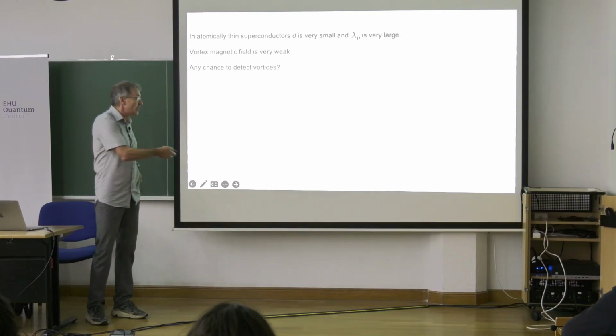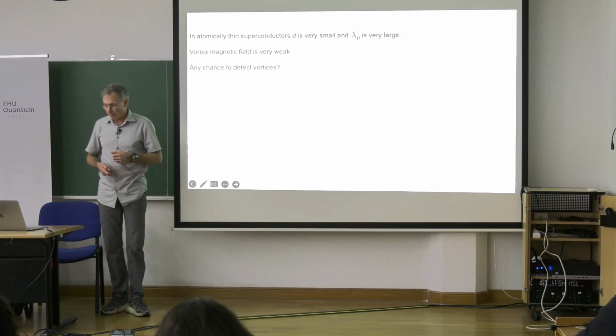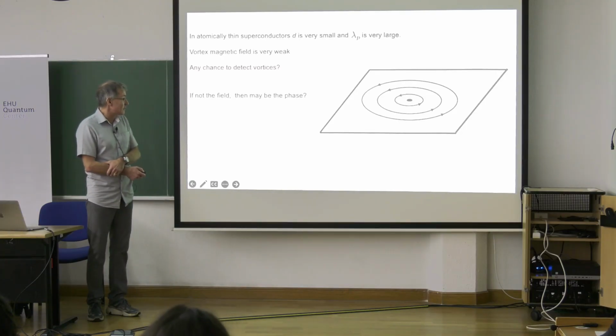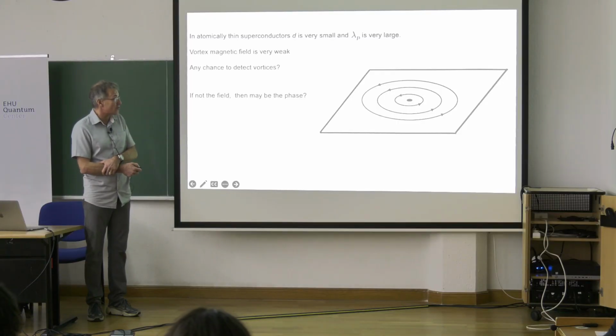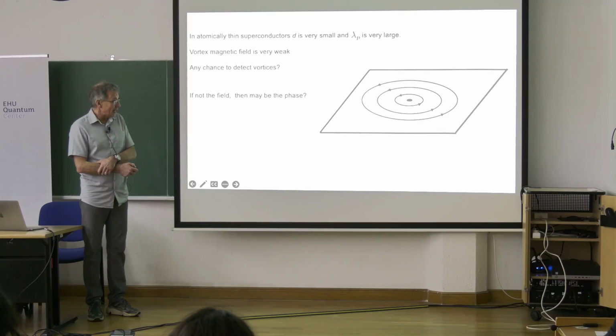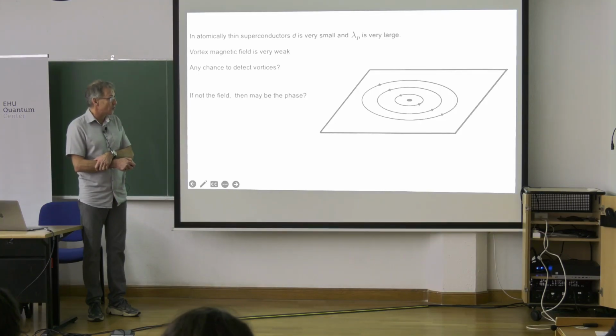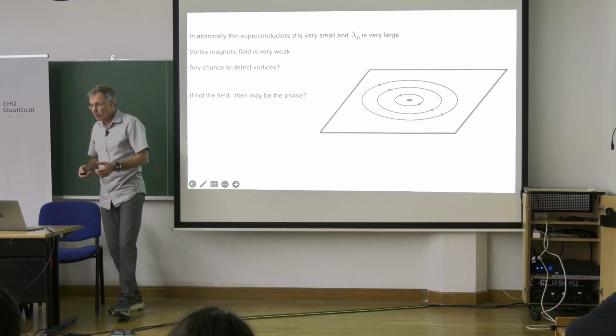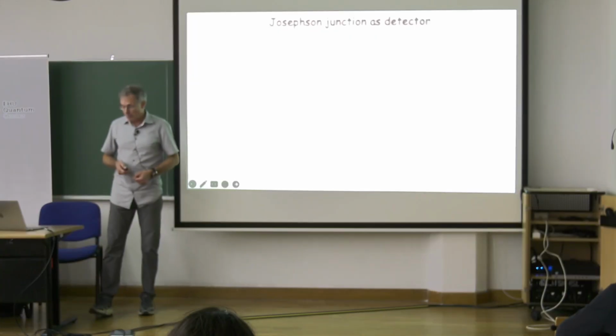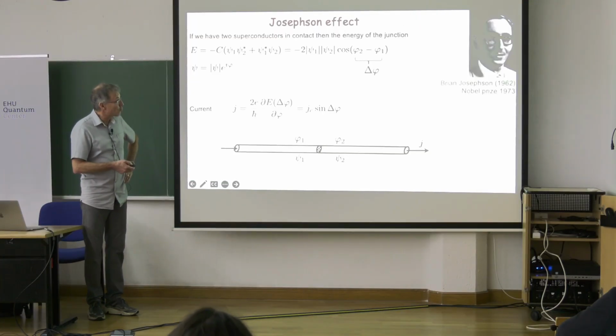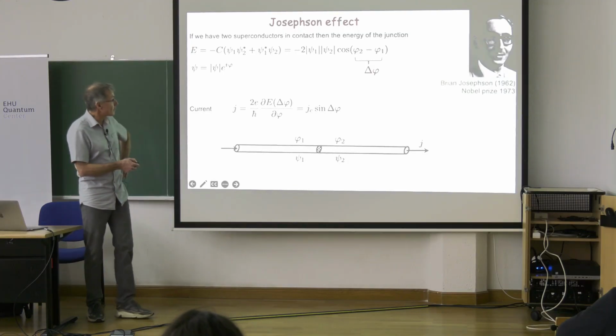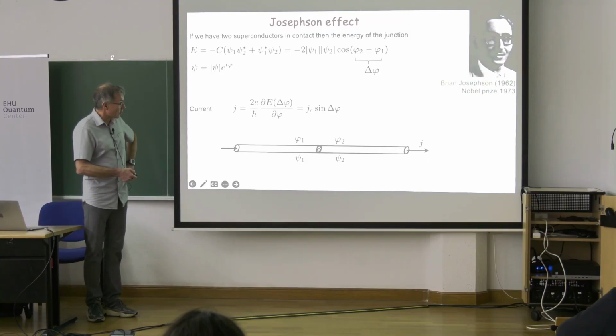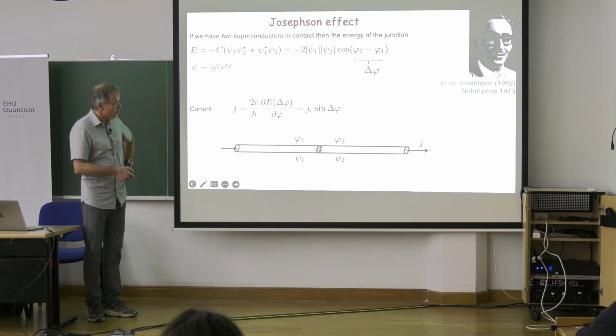Now the question: how can we still see these vortices and detect them in one way or another? The idea is that if we cannot measure the field, then maybe we can measure the phase, because the current is flowing everywhere, and so it produces phase far outside of the vortex. Now, how do we measure phase in a superconductor? Here we come to the Josephson effect, due to Brian Josephson. The simple picture: you take two superconductors with order parameters psi1 and psi2, you couple them, and you look at the energy of the junction between two superconductors.